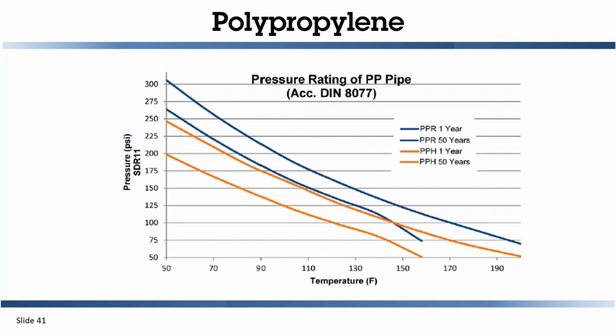Another way of looking at that is the years in service. So PPR, because it is a little more flexible, it gives a higher pressure rating across the board. So PPR for 1 year is the top line here that we see. Depending on the temperature, you have a pressure rating that corresponds. PPH is a little more brittle, so we have to be careful about overpressurization, a little more careful in the design of the PPH systems. PPR for 50-year life, easily 150 psi for a very long time at ambient temperature.